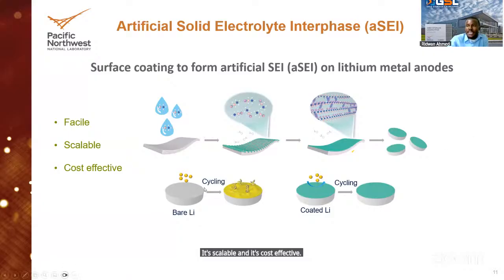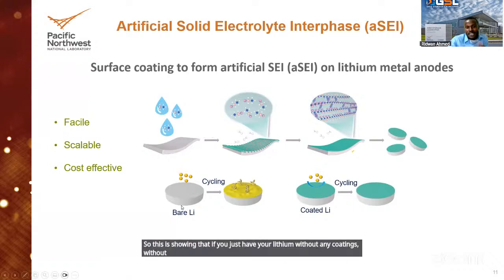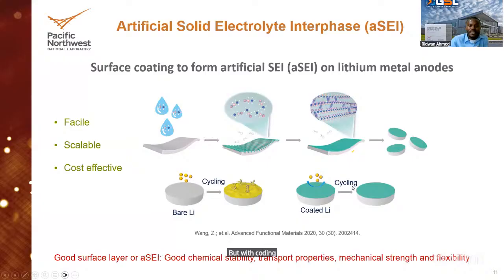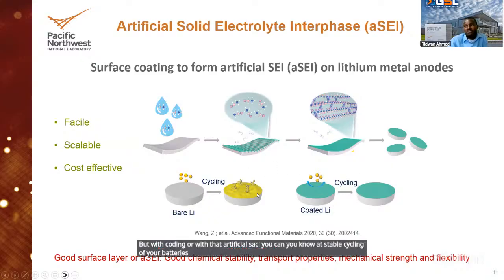So this is showing that if you just have your lithium without any coatings, without any artificial SEI, you can easily form that dendrite. But with coating or with that artificial SEI, you can achieve stable cycling of your batteries without forming all these dendrites.